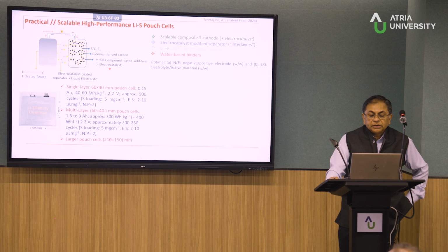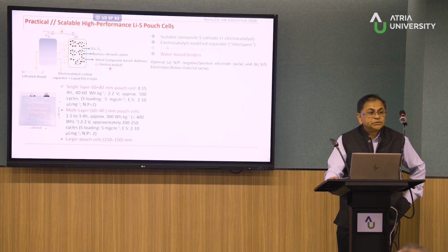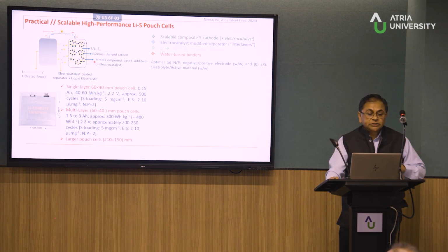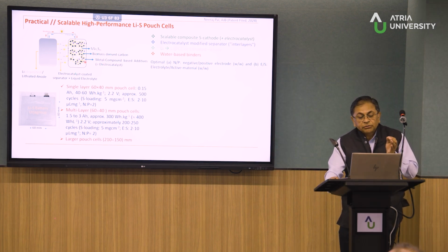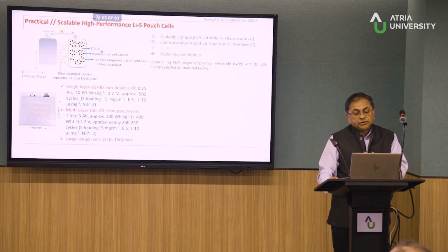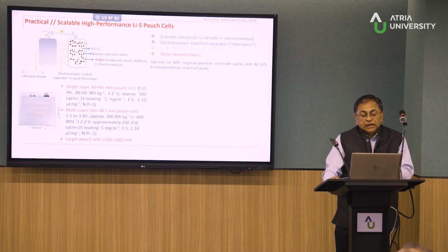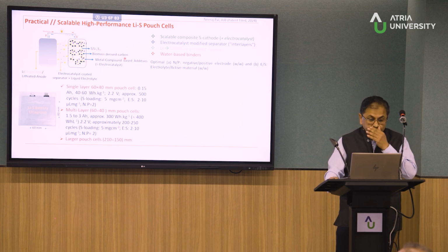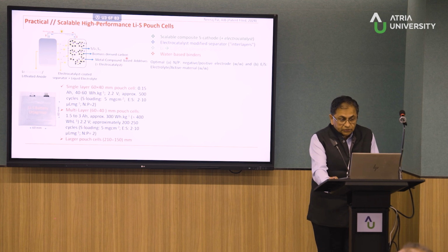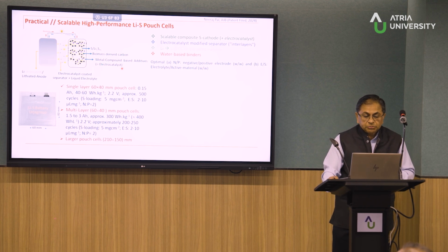I must say, we don't have that many young students here, but this is just using NCERT class 12 chemistry, right? The electrocatalysts are designed here, and we can scale them up in the lab. What these electrocatalysts do, if you add them in optimal amounts to sulfur, or let's say the end product of the sulfur-lithium sulfide reaction, mixed with biomass-derived carbon, which we are also actively looking into because you need carbon with sulfur, and the carbon has to be from a cheaper source.